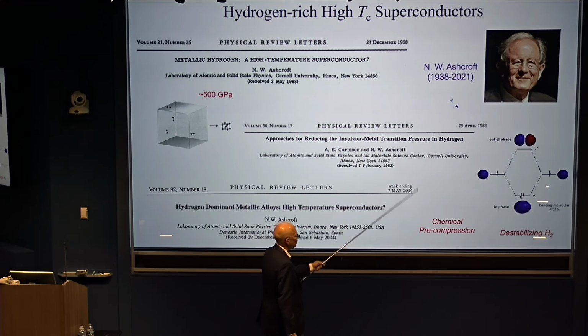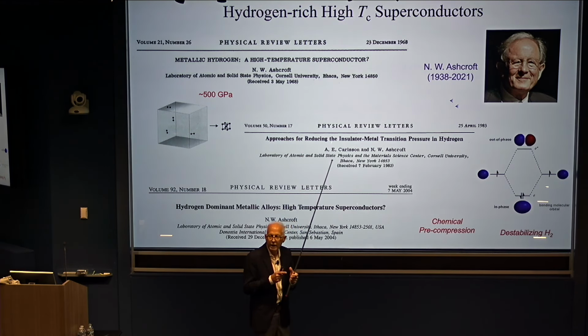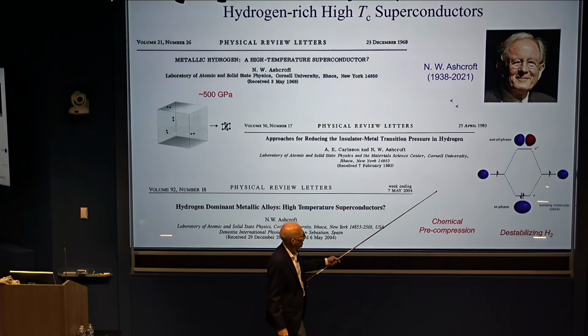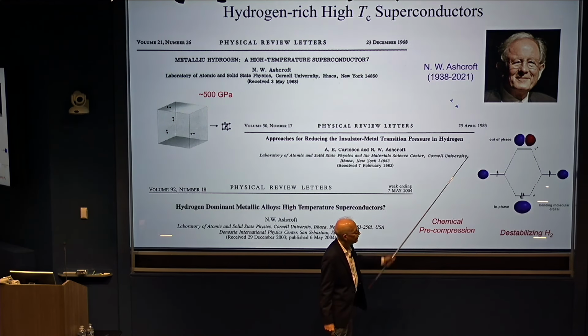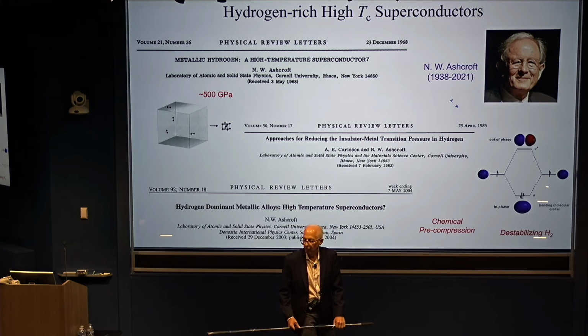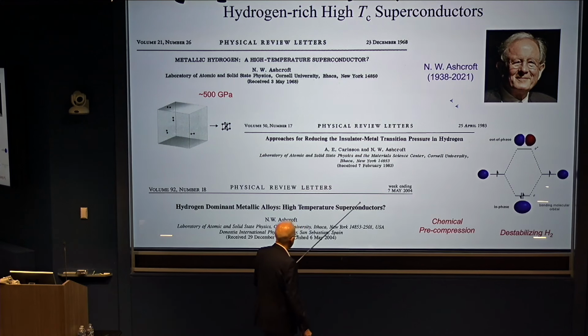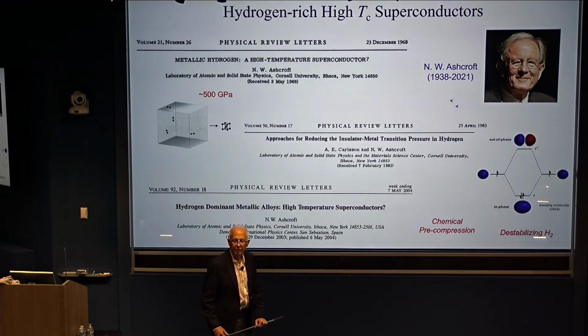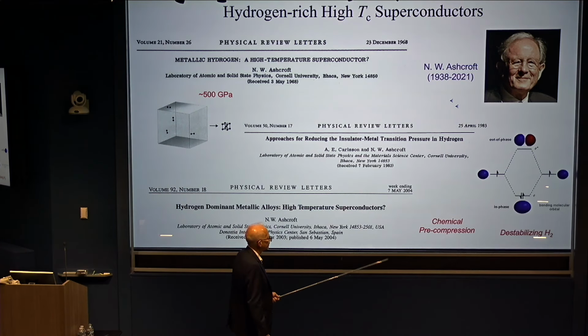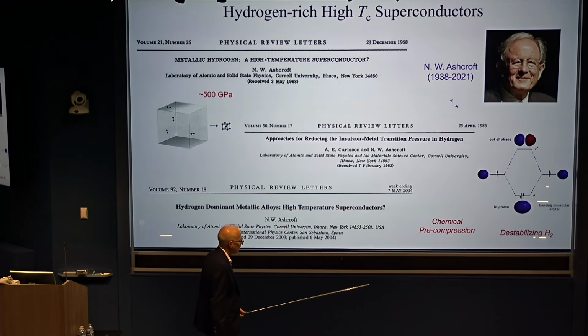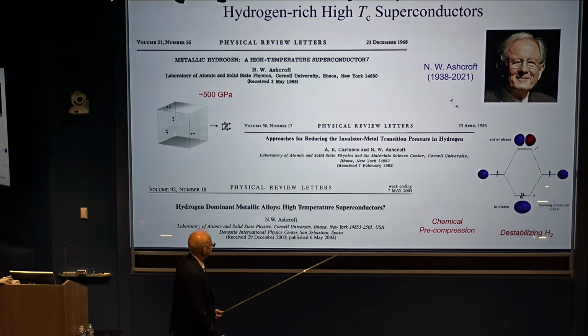You could do this with photons, or you could do this by pressure ionization, somehow ionizing atoms that would then populate the antibonding orbitals of the hydrogen. And this was more systematically formulated in this paper, where he suggested there could be whole classes of hydrogen-dominant alloys that could exhibit these phenomena that would be like metallic hydrogen, some of these really interesting properties, but exist at lower pressures, maybe in the 100 GPa to 200 GPa range.